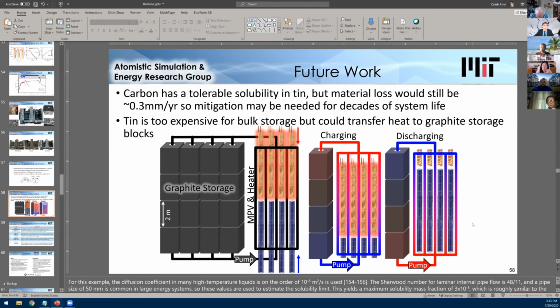Another candidate when you're using tin is tungsten. It doesn't react, but tungsten actually becomes quite soft above 2000 Celsius. So you could use it in some locations if it's needed, but graphite has high thermal conductivity, low cost, and high strength. So I think it's an ideal material both for the pipes and for the thermal storage itself.